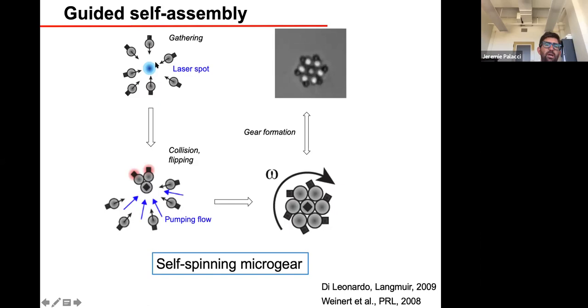Then one of the particles is going to flip on the laser spot. The reason for that is that hematite is also absorbing for blue, and so if you pass above the laser light, then you have absorption. So it means that you have less light on top than on the bottom, and so the hematite tail will migrate towards the dark as it did before.